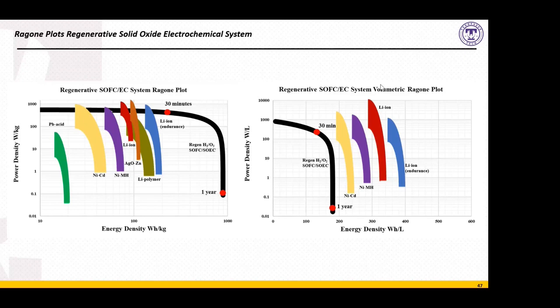Now, the pressure of the gases in this study was about 20 bar for the hydrogen and the oxygen. If developments were made where the hydrogen and oxygen could be stored at much higher pressures, at hundreds of bar, and the appropriate downregulation of the pressure of the gases before they enter the solid oxide electrochemical cell could be done, then perhaps once again the regenerative cells might compete with the battery technologies here. But these kinds of preliminary studies are useful to do before the technology is pursued in greater detail or more earnestly.